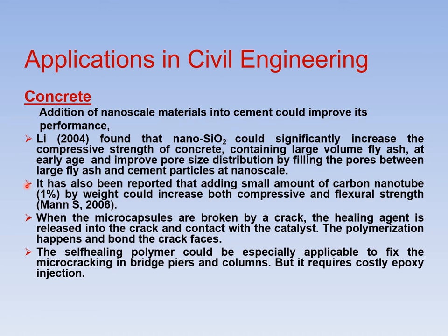It has also been reported that adding a small amount of carbon nanotube, 1% by weight, could increase both compressive and flexural strength. When the microcapsules are broken by a crack, the healing agent is released into the crack and contacts the catalyst. The polymerization happens and bonds the crack faces. The self-healing polymer could be especially applicable to fix the microcracking in bridge piers and columns, but it requires costly epoxy injection.